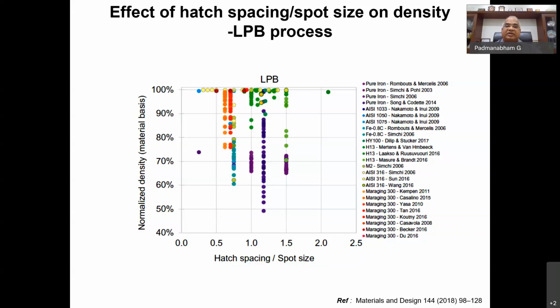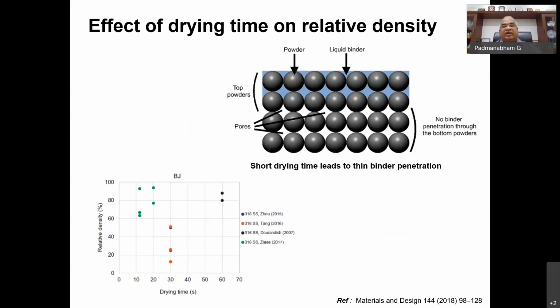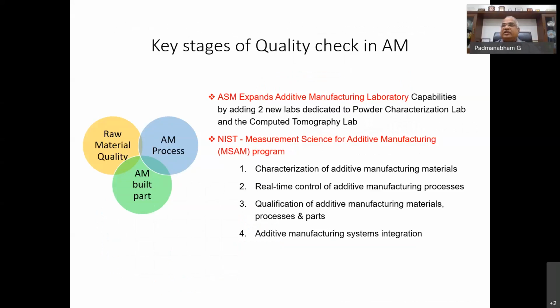This is another optimization process related R&D that you can do. Even in the case of the simple binder jetting method, the choice of your binder matters. If the drying time is too less, then the penetration into the bottom layers will get restricted and you end up with poor quality of your green compact. So you have key stages of quality check in additive manufacturing, right from the raw material quality to the process, as well as the final part itself, which has to be checked so that it is acceptable to the user.